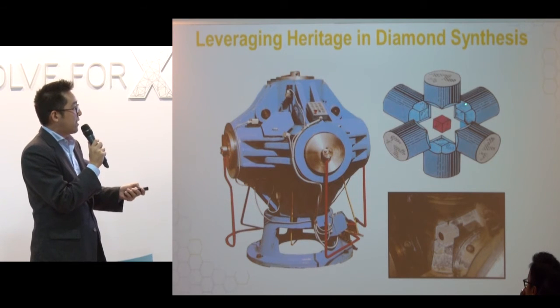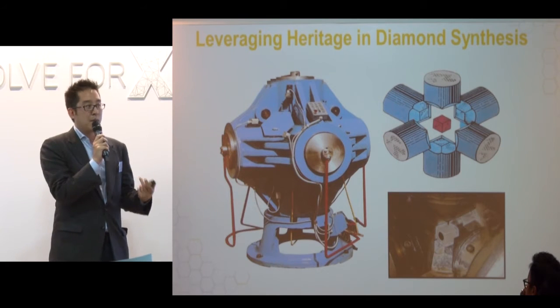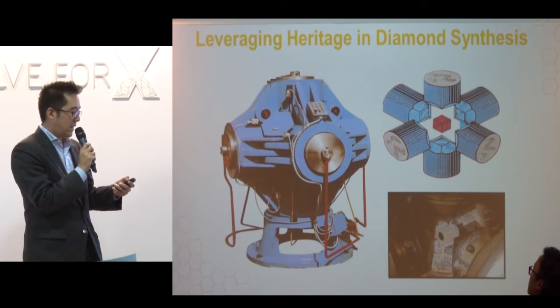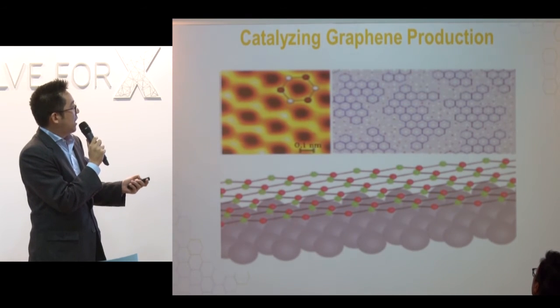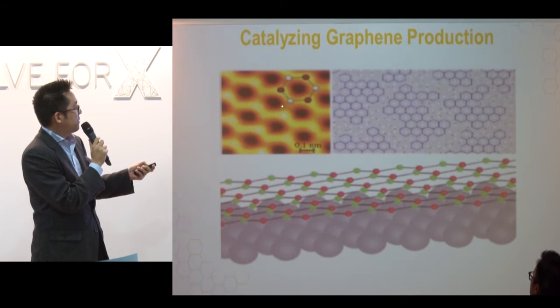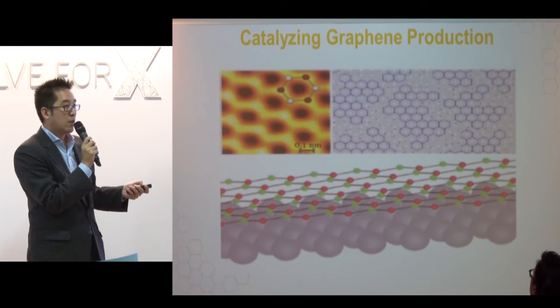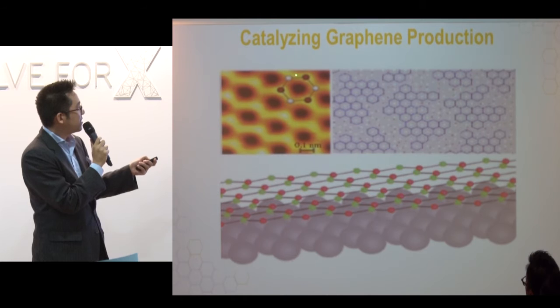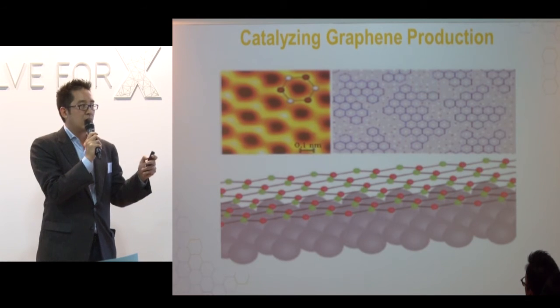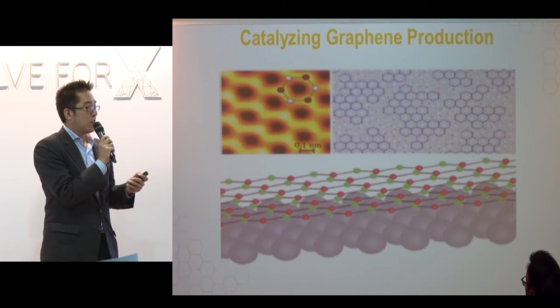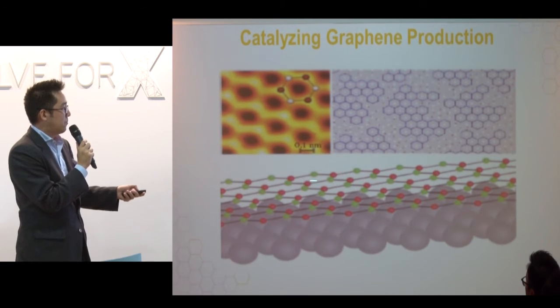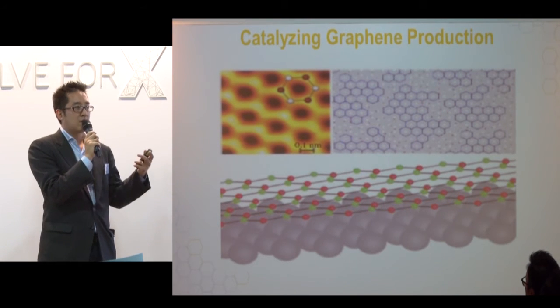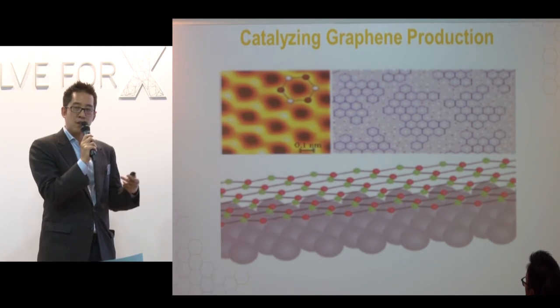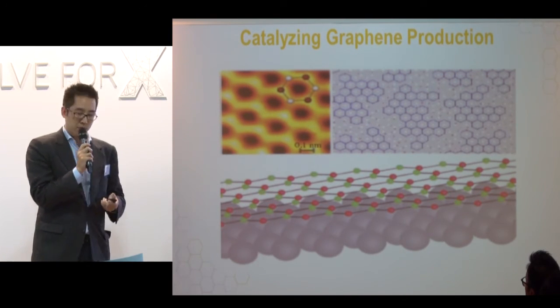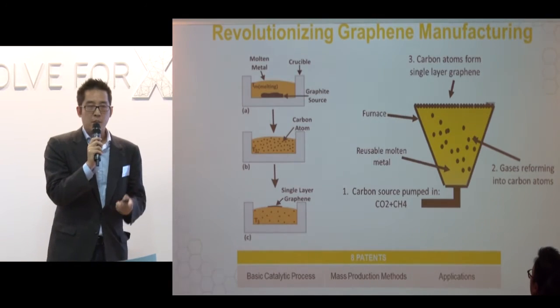So it turns out that the same catalyst system for producing diamond can be used to create graphene. Because this is an atomistic scan of the Invar powder. And if you look at it, it just so happens that these atoms are roughly on the same scale as the carbon atoms in graphene. So therefore, there's a templating that occurs. And so this system is one of the few systems that can actually dissolve carbon or dissolve graphite and then re-precipitate that in the form of graphene. So our process is very simple and our process is very scalable.